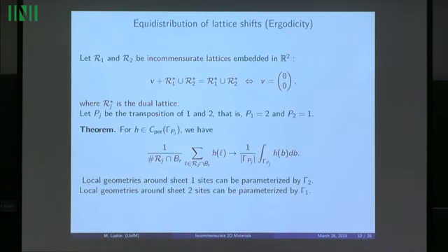Okay, and then here's our ergodicity theorem again. In this lecture, H of L is going to be the site energy. Typically in atomistic models, such as Lennard-Jones empirical models or the embedded atom method, when they want to calculate the elastic energy of an atomistic structure, it's a sum over the energy of each atom.